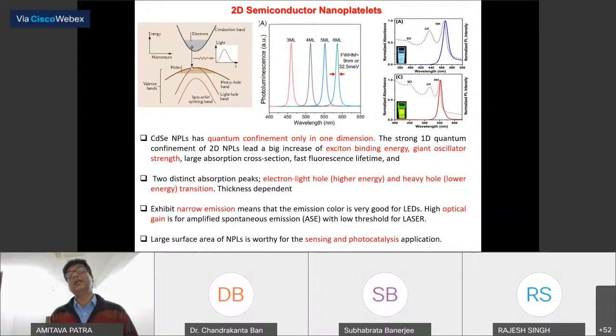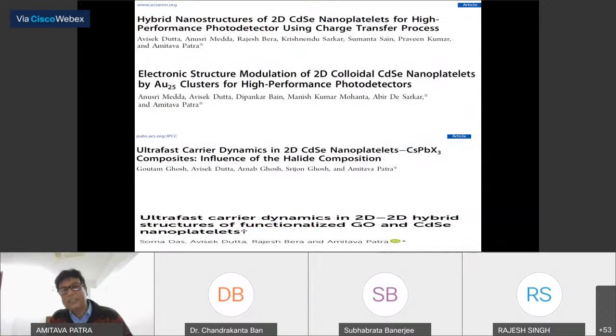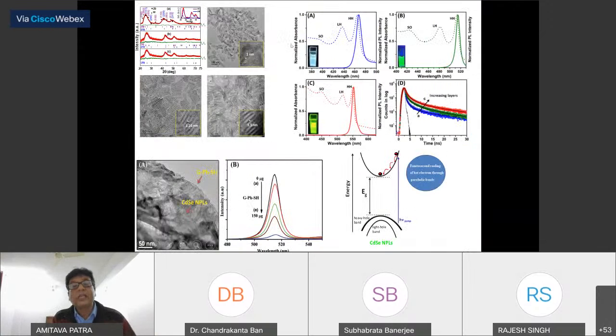Another interesting thing is why we are interested recently in the 2D semiconducting nanoplate: this has a very narrow emission band. A narrow emission band is very important for lasing application and for LED. And the binding energy of this 2D structure is very high compared to the quantum dot. If the binding energy is very high, that means you cannot separate the electron and hole very easily. That means the electron and hole recombination process is very fast because of the high binding energy. And this material can be used for LED application. We have published a couple of papers this year.